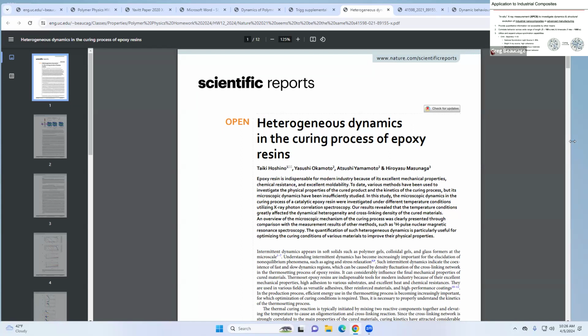So again, they're interested in curing processes. How do you take something from an epoxy, a little syringe, squirt it out, you want to stick two things together, right? That glue has to cure and harden. How long does that take? What are the processing conditions you need to solidify that? We were going to use this XPCS technique as a way to measure that curing reaction in real time, right? So that's literally the sample. This was just epoxy off the shelf that they had and were using actually on the factory floor. They designed it through just formulation science, mixing things together. They had no idea how it worked or what worked in it, right? So we were trying to go back and do some fundamental science to understand this material.